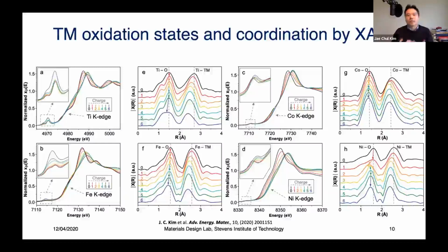So this is one example of X-ray absorption spectroscopy. If you're looking at this nickel K edge, you see the absorption edge shifting as a function of charging. This means that the oxidation state of nickel is changing. And also you see here the bond length. So this is the EXAFS pattern. You see the bond length changes as a function of charge, meaning that the nickel octahedra is distorting and recovering its symmetry upon charge and discharge.